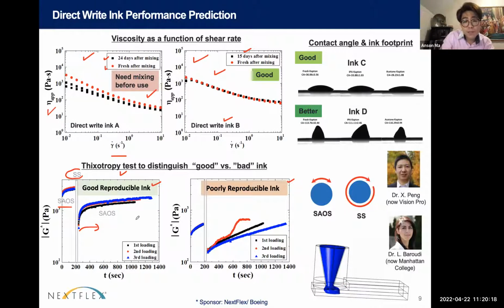By doing this test with two different inks, for example, here, this is a certain ink, it has very good reproducibility. And then in the actual print experiments, we'll also confirm that. And then the other ink you can see is all over the place. When you do it like 3 times, it's all over the place, then that's also an indicator of a problematic ink. And back then, we did these experiments, and we actually transferred some of this test method protocol to Boeing so that they can do their own rheology tests on this.